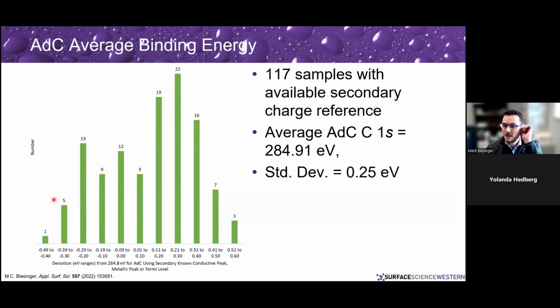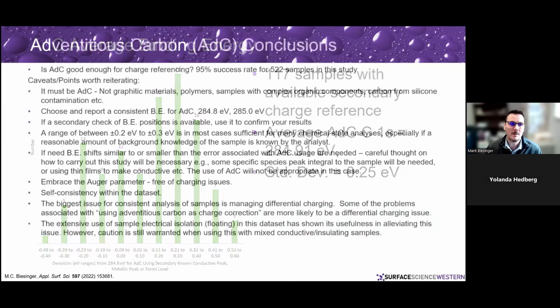And then we looked at where that positioning is, if there was a secondary charge reference available. What is the position using that secondary charge reference? So say there's a metallic peak in a floated sample or a well-known peak for something. How does that say where that carbon is really sitting? And so we found with this data set we were getting a peak position of about 284.91 with a standard deviation of 0.25 eV for the peak position for the aliphatic carbon.